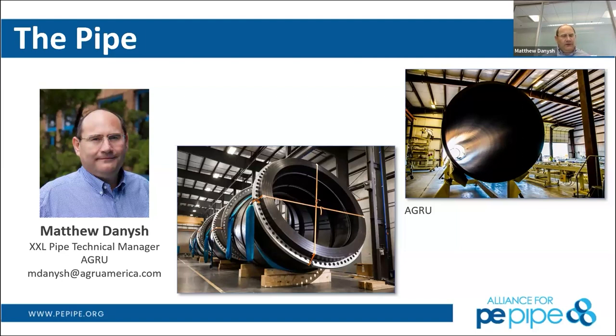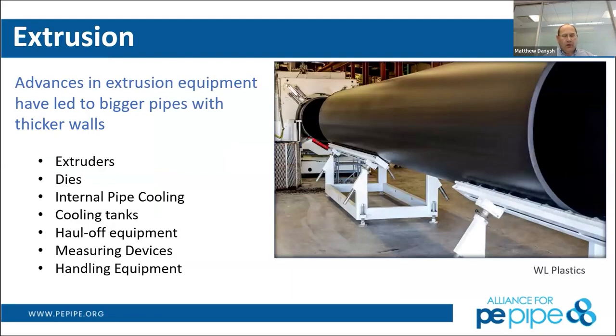Okay, so once this resin was developed for this low sag, that allows us to make large diameter pipe in heavy wall thicknesses. So diameters up to 10.5 feet are possible now, with wall thicknesses up to 6 inches for solid wall extruded HDPE pipe. And the HDPE pipe that's produced in this manner is produced basically the same as your smaller diameter pipes. It's just larger in wall thickness due to this increase in the sag resistance of these PE 4710 resins.